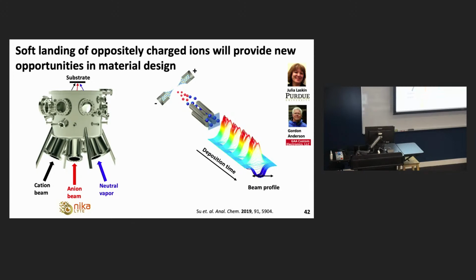So we've been looking at ways to deposit both polarities of ions, positive and negative, simultaneously. And one way to do that clearly is to have a cation and anion beam coming in at the same time to a substrate, maybe even with some background gas to build up a sort of matrix around it. The problem with this approach is that it doubles the requirements for the instrumentation and pumping and electronics, so it's a very costly proposition to do that.